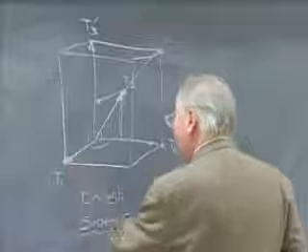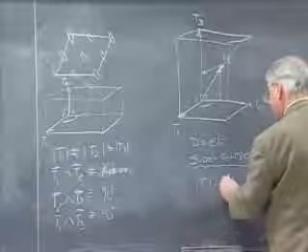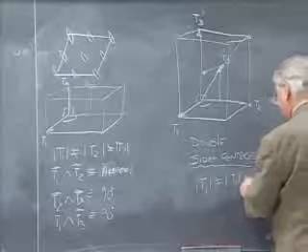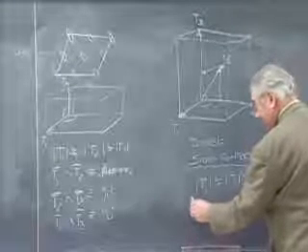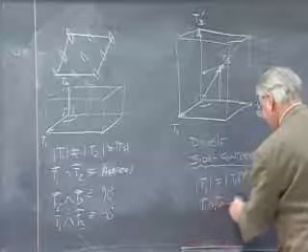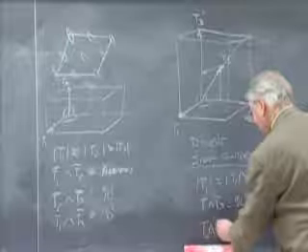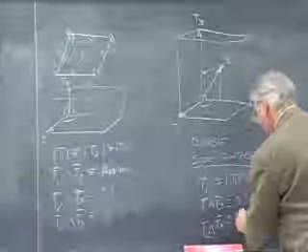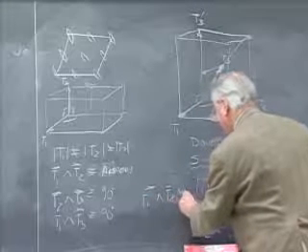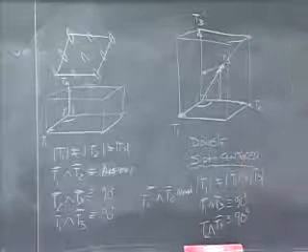And it has, with this redefinition of translations, exactly the same degree of specialization as before. Magnitude of T1 not equal to the magnitude of T2, not equal to the magnitude of T3. And it has the same specialization of the angles. The angle between T1 and T3 is exactly 90 degrees. The angle between T2 and T3 is exactly 90 degrees. And the angle between T1 and T2 is general. General, but by convention, we'll assume the obtuse angle rather than the acute angle.